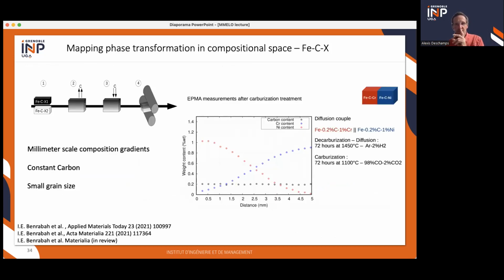So this again involved making compositional gradients. Here it took us about 2 years to find out how to make a good composition gradient. So I won't discuss all the experimental hurdles that you need to solve. If you're interested, you can look in the papers and we can discuss that afterwards. But basically, if you want to make good experiments, you need millimeter scale composition gradients, a small grain size, of course, no decarburization and so on, and a constant carbon throughout the composition gradient.